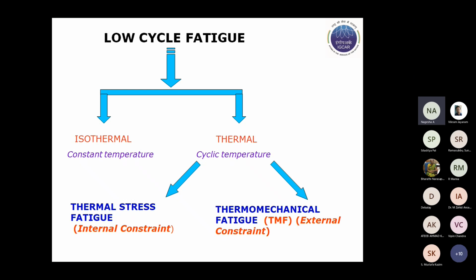The underlying assumption in this is that the peak maximum temperature cyclic data would give rise to a conservative life estimation. However, in the recent past, several studies have established that this need not necessarily be a conservative design approach. Hence, there has been a stress in recent years to generate data considering the temperature cycling that is actually happening in service. So, actual testing should be a thermal fatigue test rather than an isothermal cyclic test.